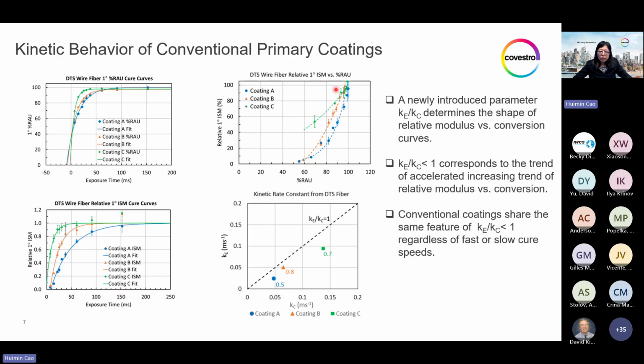But in terms of the shape of the curve, they all share the same feature, which is categorized as the accelerated increasing shape. That means the rise of modulus gets sharper and sharper at the last stage of the conversion. This is the feature making the coating property very sensitive to the processing condition, even when you thought it cured very well, reaching 90% of the cure degree. And the sensitivity of modulus rising is actually the highest in the last 10% of the cure.